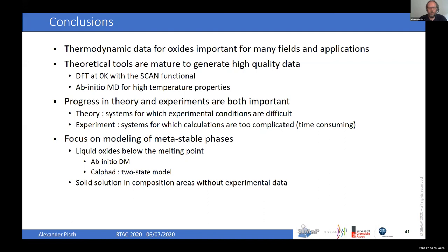The progress in theory and experiments are both important. In theory, we can use it for systems for which experimental conditions are difficult to install. As I've shown for the alkali oxides, which are so reactive with respect to CO2 and water vapor, it may be much better to do calculations than to do the experiments. And we tried that. We tried now for 1.5 years to get something out of it and still haven't succeeded to get something reasonable out. So sometimes calculations are quicker.